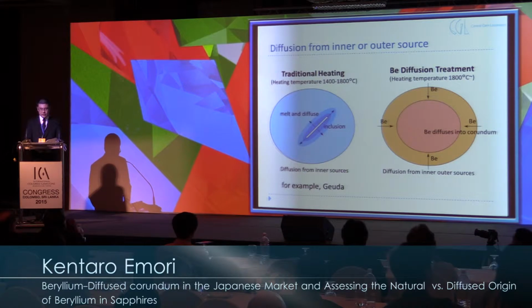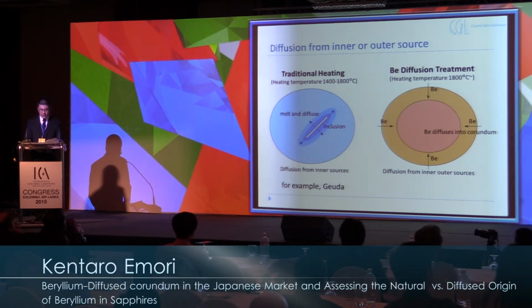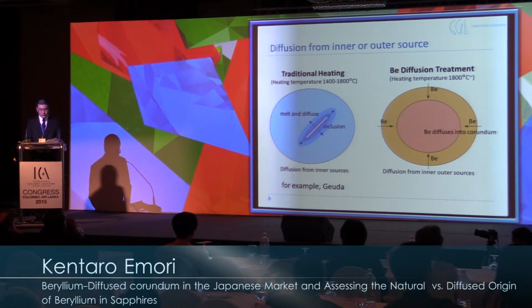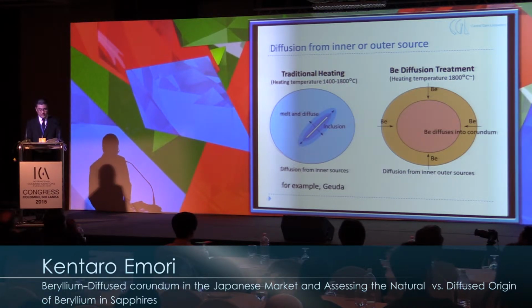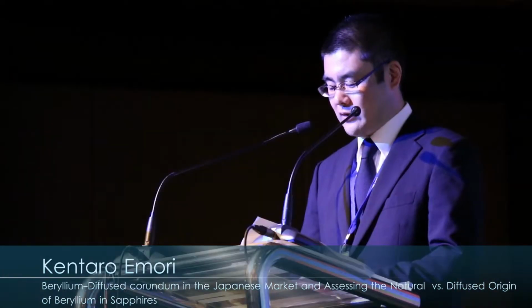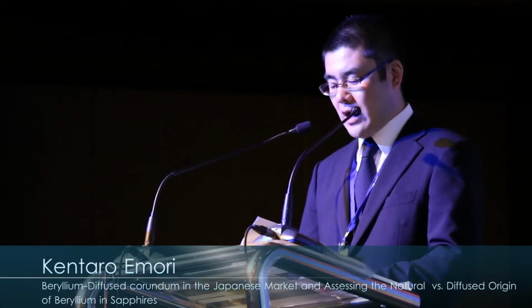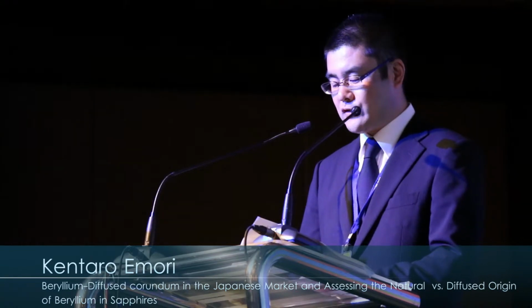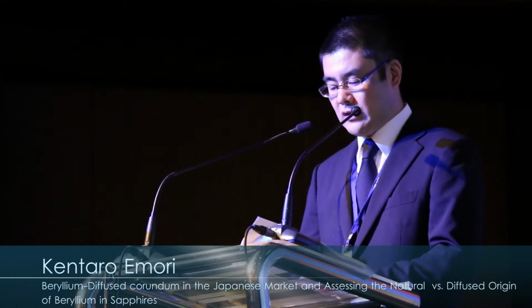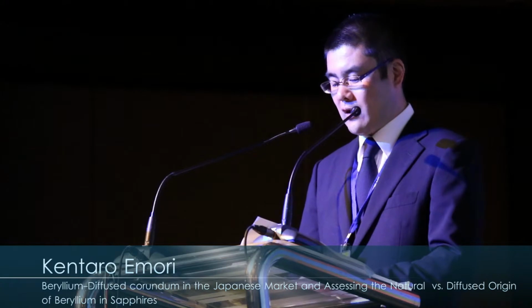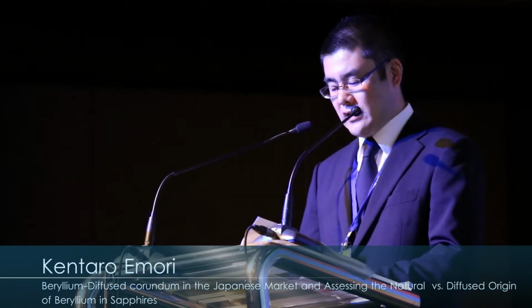The right figure shows the diffusion from outer sources. Elements in materials surrounding corundum diffuse into corundum. The beryllium-diffused corundum treatment is a case of this treatment. When the corundum is heated, elements from outer sources diffuse into corundum, and corundum changes its color. This heating is done over 1800 degrees of temperature.